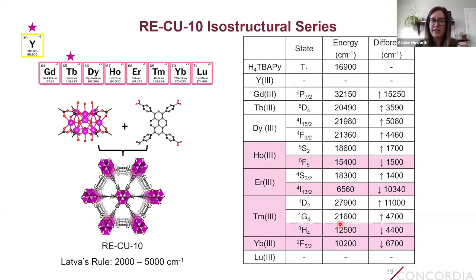And so in addition to studying yttrium and terbium Cu10 as photocatalysts for the detoxification of sulfur mustard, we also wanted to learn and understand more about this process and these types of catalysts, because the more we can understand about them, the better equipped we are to design better and better catalysts for this application. And so one thing we also wanted to see is, if we made the MOF Cu10 with all of these different lanthanoid analogs, ranging from gadolinium to lutetium, how would the potential for linker to metal energy transfer in these MOFs affect the photocatalytic results that we see?